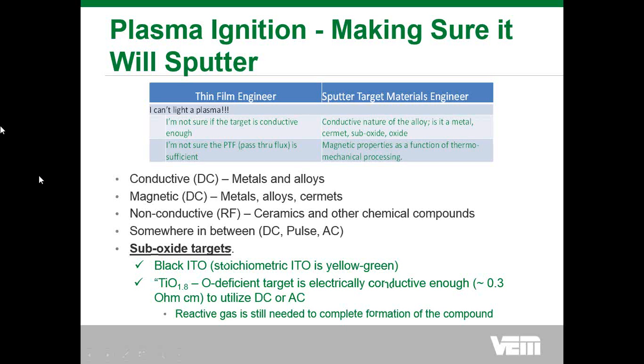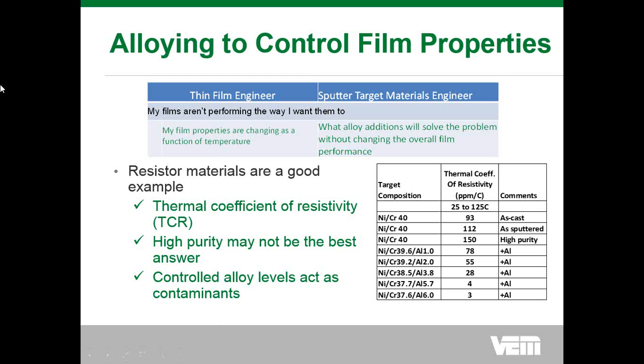Looking down that table, essentially what we're doing is intentionally adding aluminum to that nickel chrome alloy to intentionally make the material effectively less pure. And you see, as a function of the amount of aluminum that has been added to the nickel chrome alloy, the thermal coefficient of resistivity can be dropped down into single digits. So again, it's the idea of understanding what we can do with the target material that helps the thin film engineer control the properties that they're trying to control in their devices.